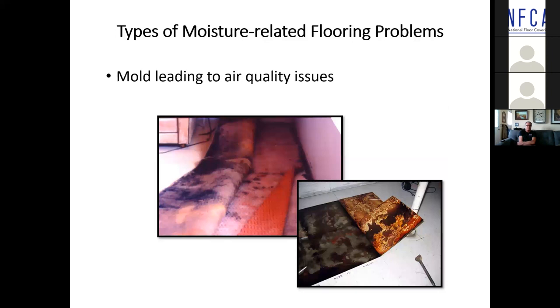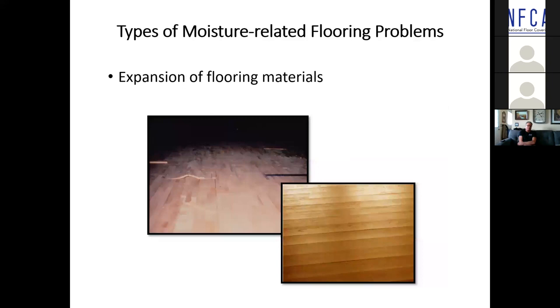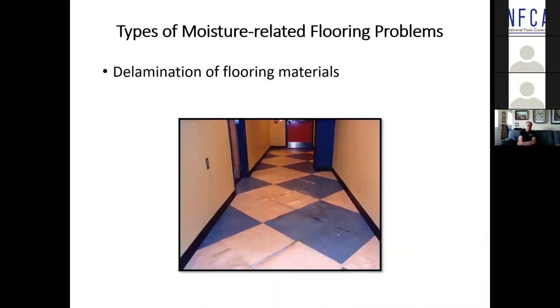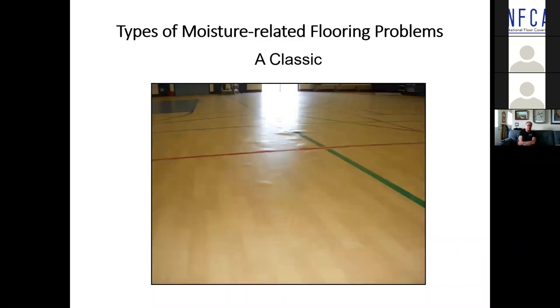Moisture can contribute to the development of mold, which in turn can become airborne and affect people's health. Very serious issue. Moisture alone can cause flooring materials to expand and delaminate. And here's a classic. This is that same picture you saw a minute ago where you see raised blisters in a sheet vinyl made to look like maple floor.